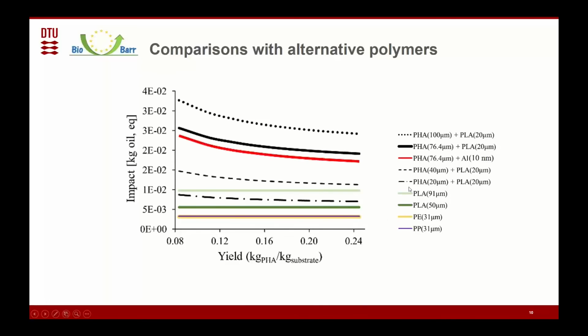So what we can conclude from this figure is that if the yield is improved, PHA of thickness comparable to the thickness of currently used polymers can compete with PLA. Not quite there yet in comparison with PE or PP, but it's not very far.